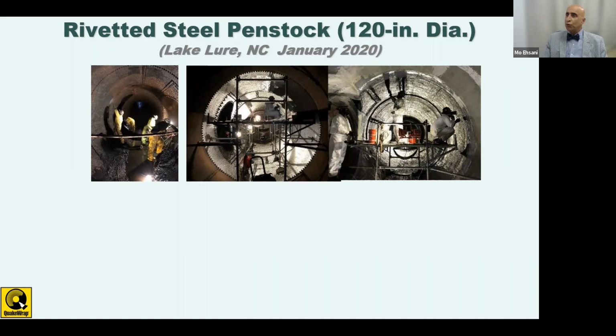Another point to note is that if you have a riveted pipe, for example, like this one, we have to feather those protruding rivets so that we smooth those surfaces, and that is done as a first step by putting a mix of epoxy and mixing it with sand. We can then coat over those rivets and cove them to get them nice and smooth, and then the fabric is applied on top of that.